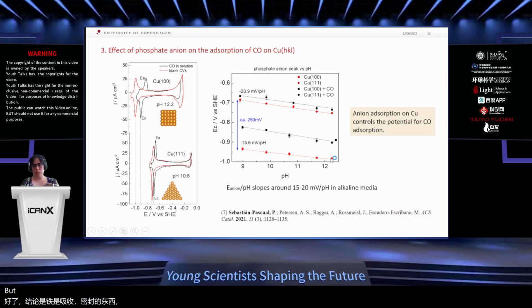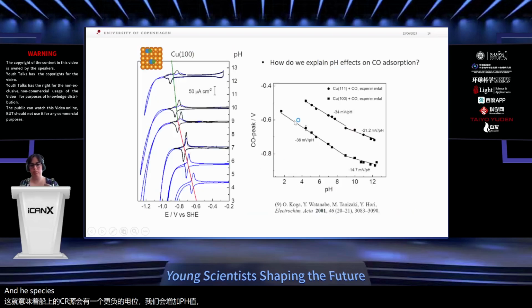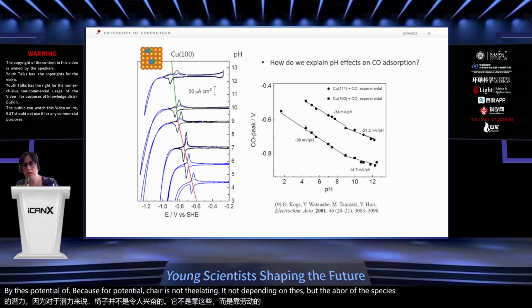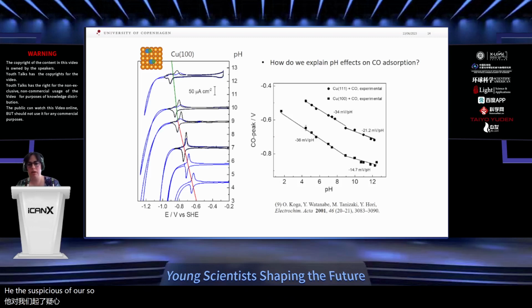But we see that there is a pH dependence on the CO adsorption. This means that the CO adsorption shifts to slightly more negative potentials when we are increasing the pH. And this pH dependence is even stronger in acid and neutral media. So this pH dependence cannot be explained by differences in the potential of zero charge, because the potential of zero charge is not dependent on pH. But the adsorption of these species that are adsorbed depends on the pH.